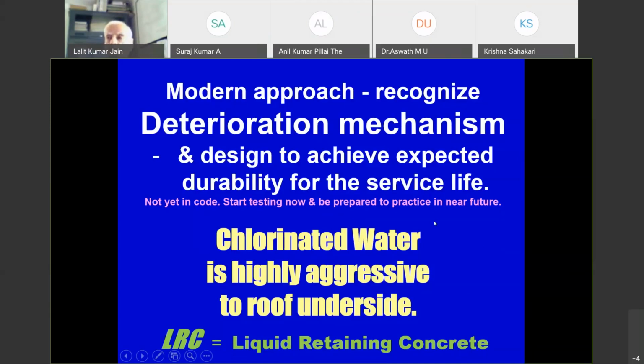Once corrosion starts, it is a matter of a few years, something like 5, 6, and if things are very favorable, very good concrete, it will be 10 years, that steel will be corroded extensively. So corrosion start is more or less the end of our life. These approaches will come shortly. In BIS, we are revising IS 456, and as soon as the revised IS 456 is out, it will talk of these different mechanisms of durability loss, and we'll have to design as per that.